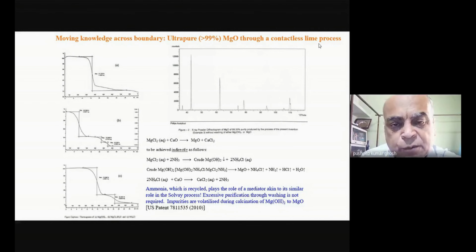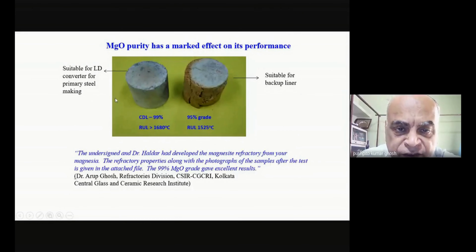So effectively, the net stoichiometry is still magnesium chloride plus calcium hydroxide, giving you magnesium hydroxide plus calcium chloride, but it is done indirectly. And because of that, we were able to make a super pure magnesia. And just to give you an idea, this is the magnesia that we could make through this contactless process. And this is the magnesia which we were getting earlier. And when it was evaluated, what they basically said is that this stuff is now suitable for primary steel making. And all you can see is that we've shifted knowledge across boundaries. That's it. Nothing more than that.